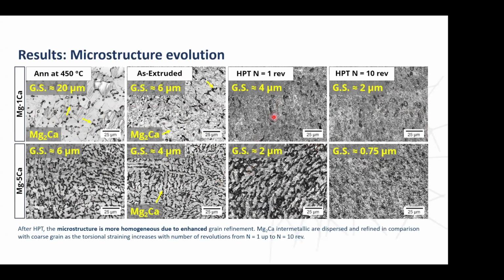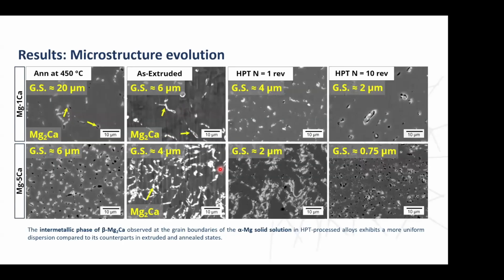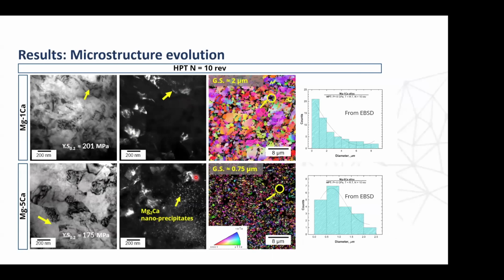And you can see here that the grain size seems to be reduced, and the dispersion of the particles is carried out, especially in the 1 calcium alloy. We can see that the particles are well dispersed and finer in size. And this is one of the important aspects to control: the magnesium two calcium particle size and dispersion. And you can see it probably more clearly here in backscatter images in SEM. So controlling the particles, that's important.